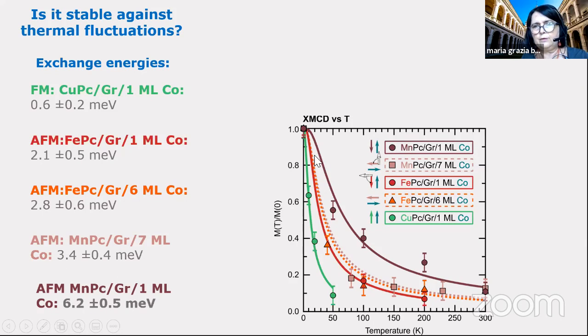And then the best configuration, where you really can have a good, non-negligible exchange energy at room temperature, with the magnetic moment able to resist and stay at room temperature, is for manganese. In this configuration, why is this the most stable configuration? Because you have a high magnetic moment on manganese, and the easy magnetization axis on manganese for one monolayer is aligned to the easy magnetization axis of cobalt. So the maximum coupling you will have is when the easy magnetization axes are aligned. It is an antiferromagnetic coupling, no? But with the easy magnetization axis aligned.